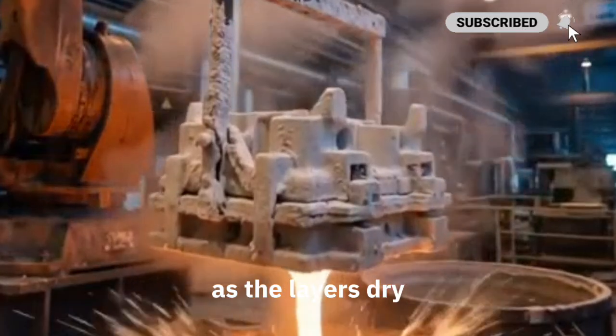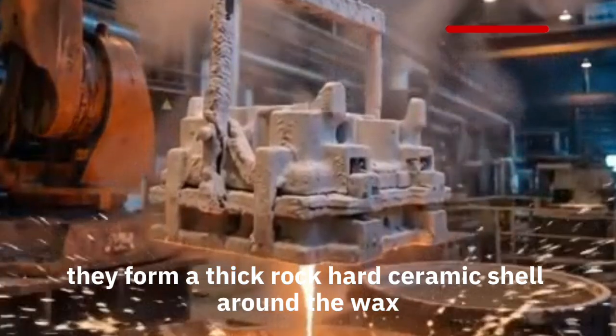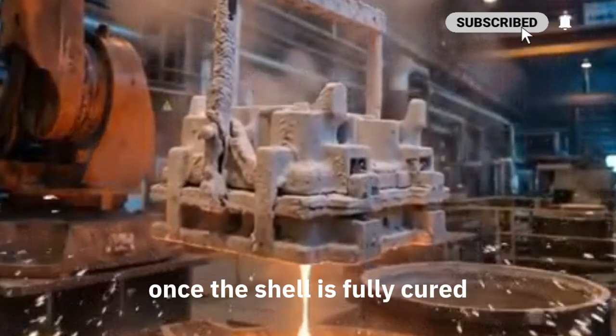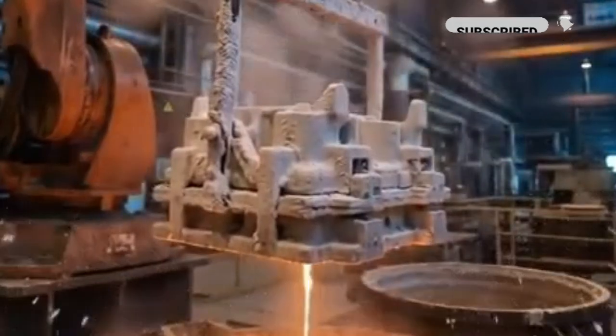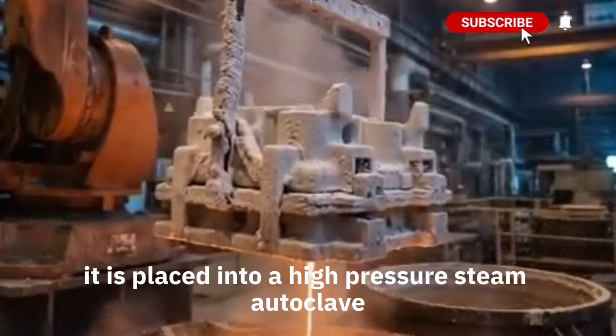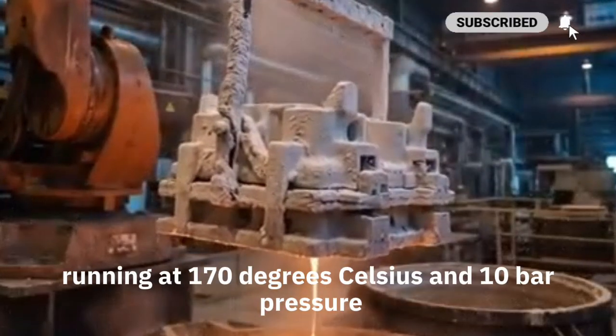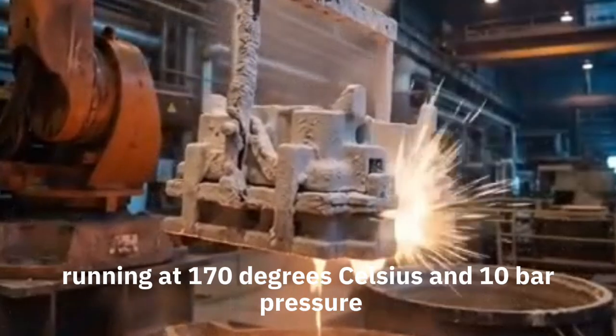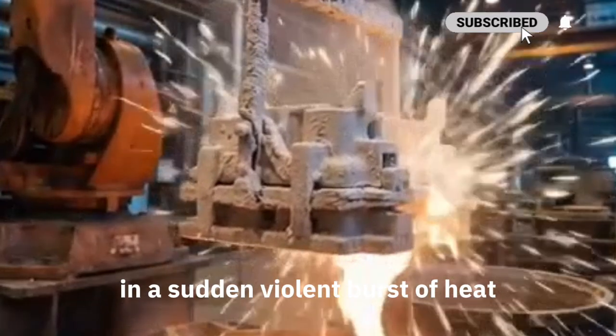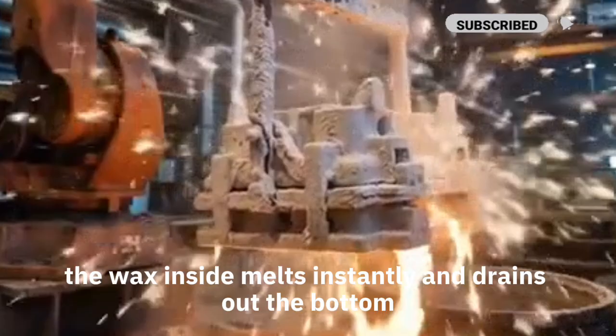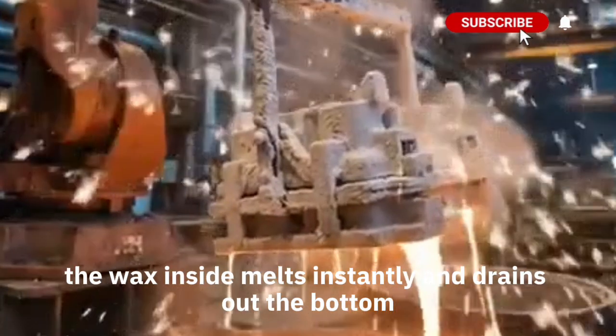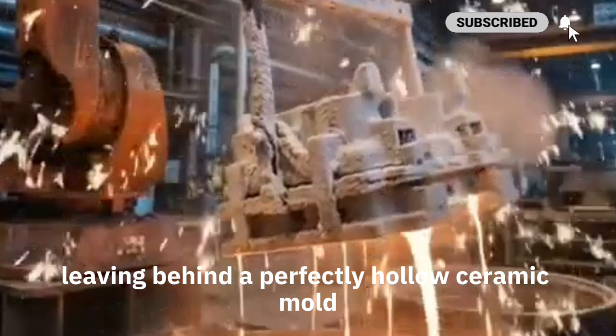As the layers dry, they form a thick, rock-hard ceramic shell around the wax. Once the shell is fully cured, it is placed into a high-pressure steam autoclave running at 170 degrees Celsius and 10 bar pressure. In a sudden, violent burst of heat, the wax inside melts instantly and drains out the bottom, leaving behind a perfectly hollow ceramic mold.